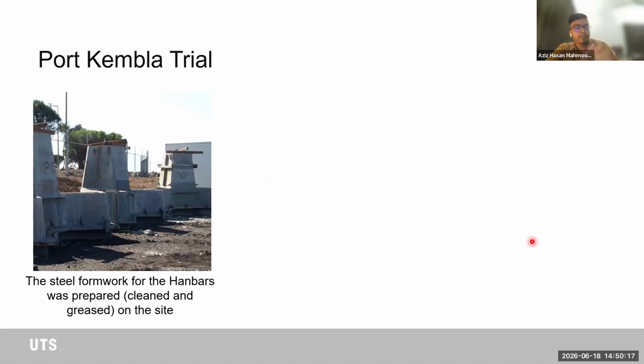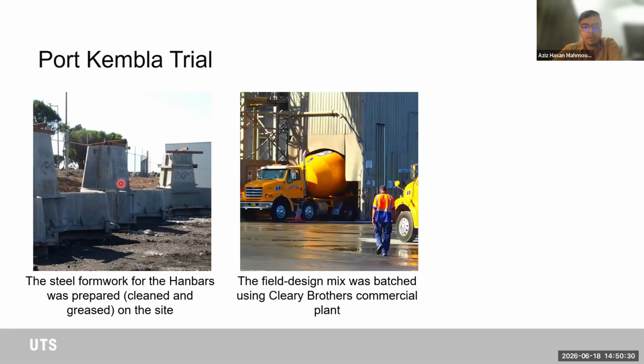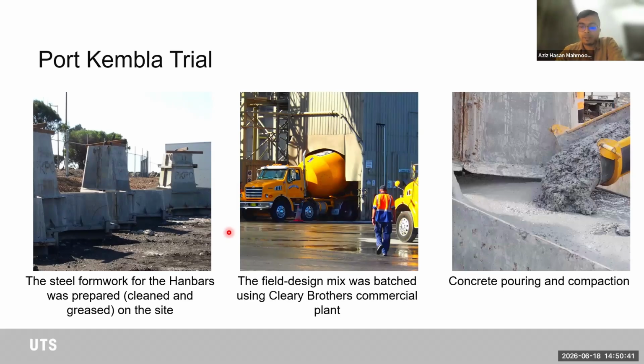So a bit more into the Port Kembla trial, the steel formworks for the Hanbar was prepared. You see it's more like a three-legged unit, each of them. And we used a field mix design, which was batched using Cleary Brothers commercial plant, which is about 15 minutes away from the site. And we poured the concrete into two segments.